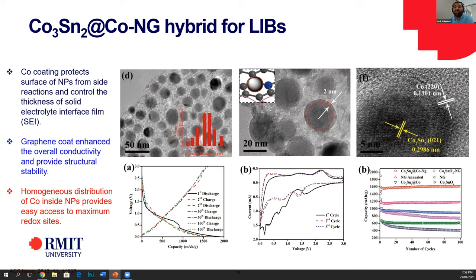So if you look here, we have a cobalt coating on the surface of the material. Once the cobalt coating is inert, it will not do any side reactions. It's also a very tough material. It will also not let a lot of structural changes happen. So ultimately, we have a very exceptional performance of the material for battery. We have excellent stability, excellent rate capability, and a high capacity storage in the material because we can preserve the structure, and we have created extra sites over there.